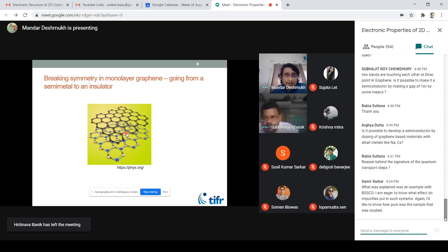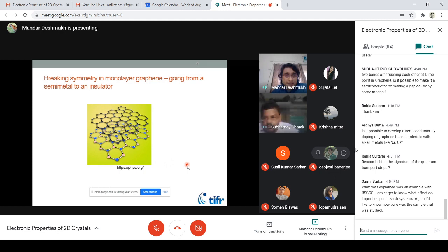So the most reliable way to make a band gap in graphene is to break the inversion symmetry, which is to realize a system where there's one chemical species here and another chemical species there. So just starting from graphene, you have to figure out a chemistry method or some other material science technique of changing the chemical environment here and not doing it here. It may become possible in future. I cannot say that, but in some way it's already realized through something like boron nitride. But boron nitride does not satisfy the criteria that you prescribe of a band gap of 1 electron volt,